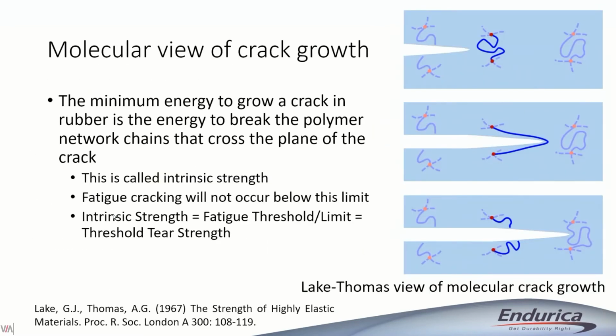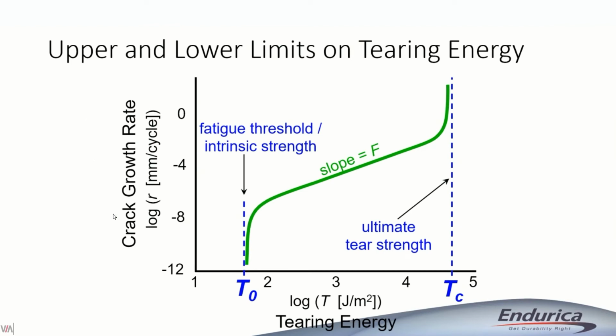So the question then becomes, we know rubber has a fatigue limit, and I know that if I stay below it, I've got infinite life. How do I measure that intrinsic strength? Now, I'll call it a naive approach. A naive approach might be to get a fatigue crack growth test system, servohydraulic, and run a fatigue test and take this curve and go to lower and lower and lower crack growth rates until you approach this limit. I call that naive because if you try to do that, you end up running really, really, really long tests, and you end up burning huge amounts of time on expensive machines.